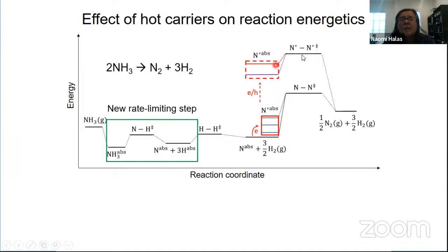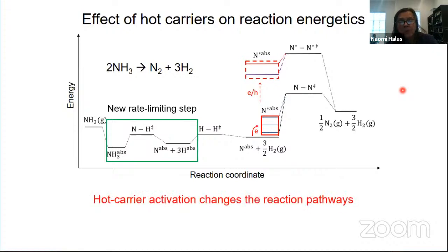So this is no longer the limiting step for the reaction, but actually breaking nitrogen-hydrogen bonds, much lower energy, is the rate limiting step for the reaction. So we're really changing the course of the reaction by doing this in an antenna reactor and by using a physical mechanism, which is the actual desorption of the adsorbed species on the surface of the nanoparticle.